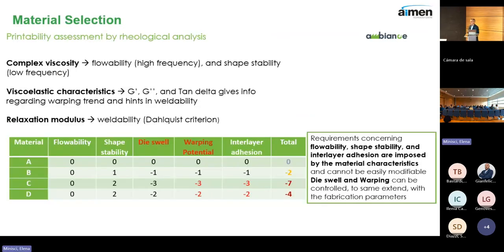So the first thing we did was to apply a protocol that we have developed internally at AIMEN, based on parallel plate rheology. In this way, we assess the potential of the material for making the transition from small scale to large scale 3D printing. We evaluate three main parameters. First is the complex viscosity. The complex viscosity gives us very interesting information regarding the flowability and the shape stability of the material. Flowability is how the material flows through the nozzle, and shape stability is the ability of the material to retain its shape when it exits the nozzle. Both are critical parameters in 3D fabrication.